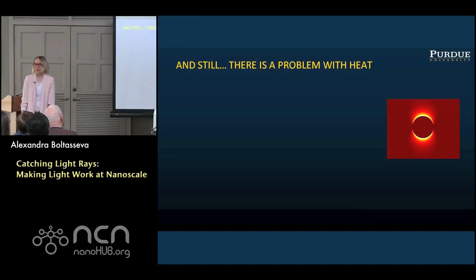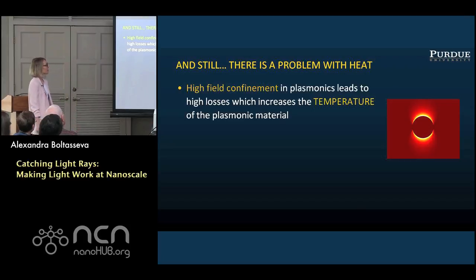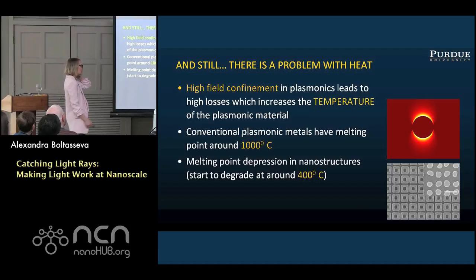Okay. But there is still a problem. As I said, if you focus light down to the nanoscale, optical trapping or not, things heat up. And the problem is really that the field confinement is so high that even metals like gold and silver that have a high melting temperature would be destroyed. Part of this is that the melting point in nanostructured material is much smaller. So it's enough to heat it up to 300 or 400 degrees to see that your gold structure is completely ruined.